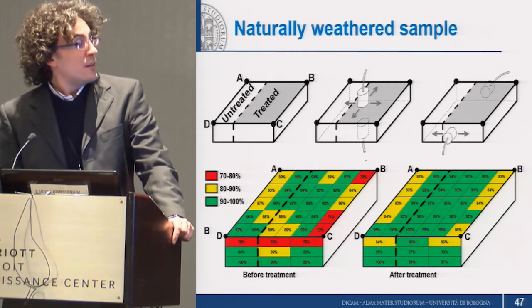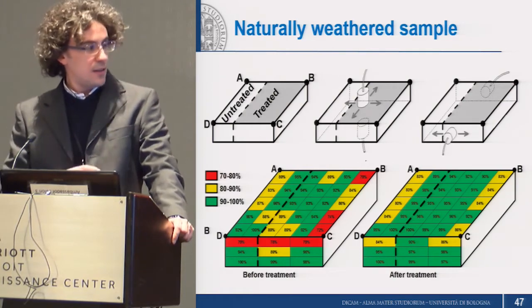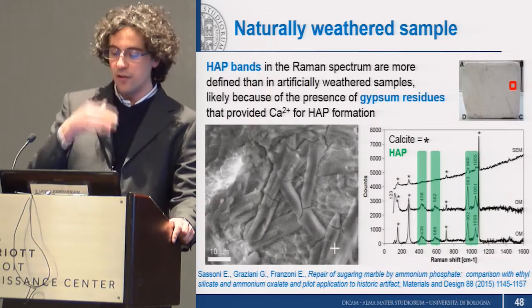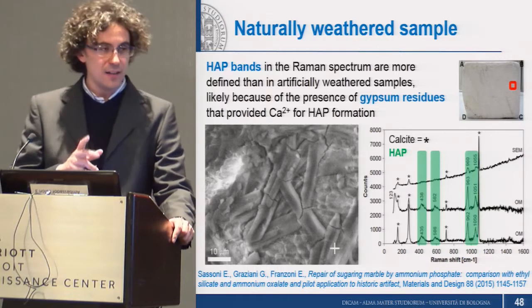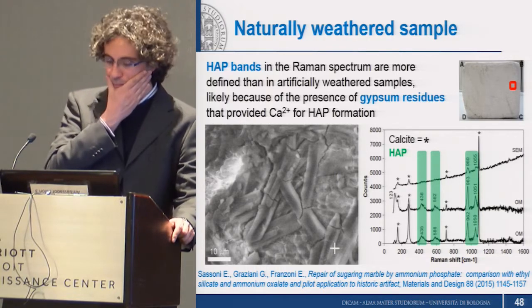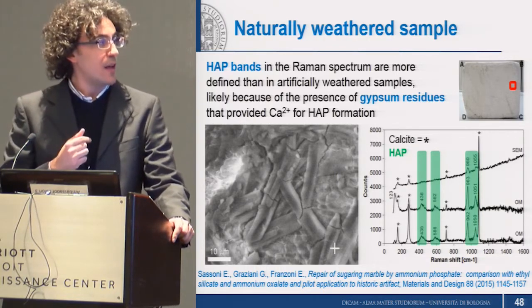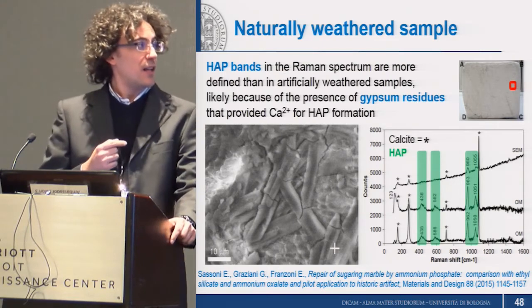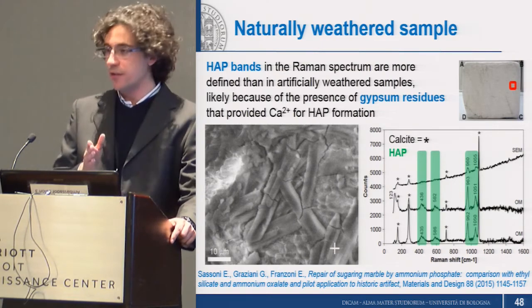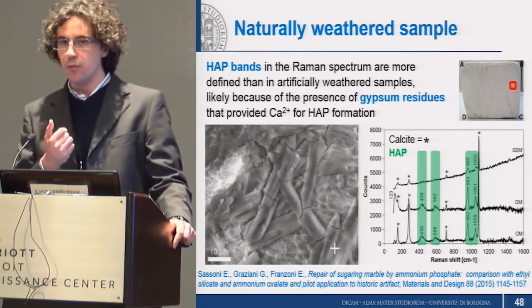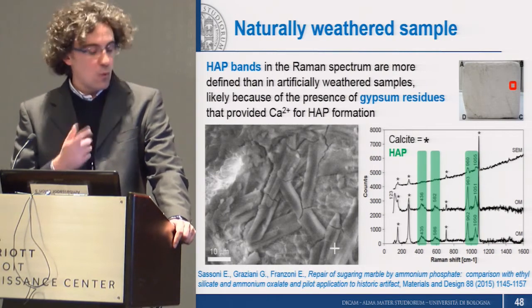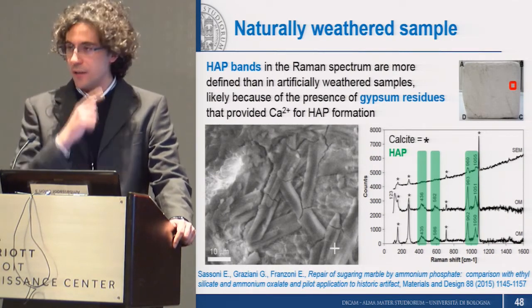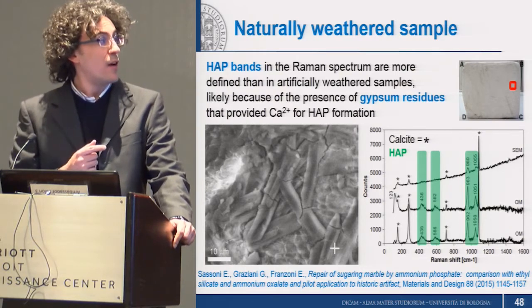What was interesting in this case was that the mineralogical phases that we found were slightly different than in the case of the artificially weathered samples, meaning that in this case, we only found hydroxyapatite, which is the mineral that we actually wanted to form, while no octacalcium phosphate and no tricalcium phosphates were found.